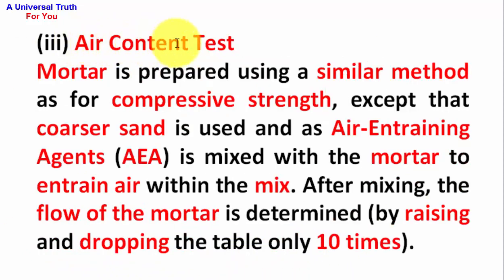Air content test. Mortar is prepared using a similar method as for compressive strength, except that coarser sand is used and an Air Entraining Agent, AEA, is mixed with the mortar to entrain air within the mix.